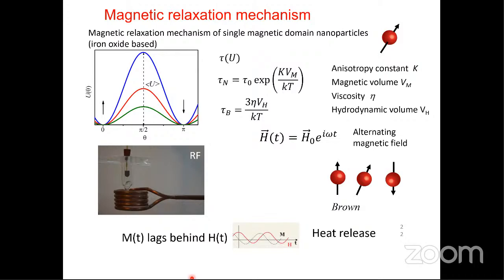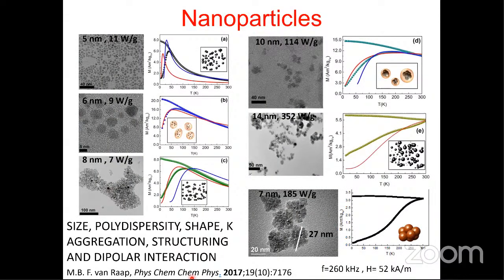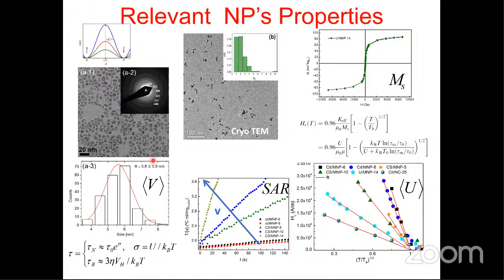We have studied over the years many nanoparticles produced by different methodologies. We have analyzed size, polydispersity, shape, anisotropy, aggregation, structure, and dipolar interaction influence. We have analyzed everything, as many people in the community have, and at the end we ask ourselves which are the relevant nanoparticle properties that we can use to predict the behavior of a real colloid, not a colloid that has no interaction or no aggregation. One real colloid that can be used in the clinic. Which are these properties? Because this important energy barrier is affected by all of these properties I just mentioned: anisotropy, size, aggregation, dipolar interaction.